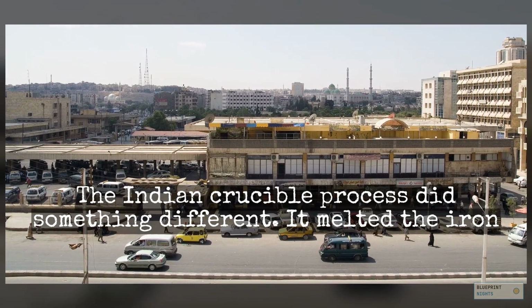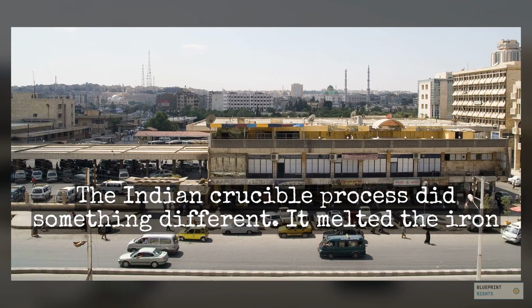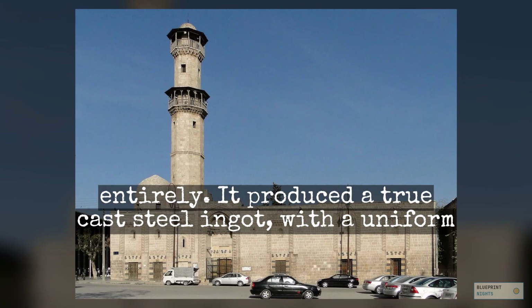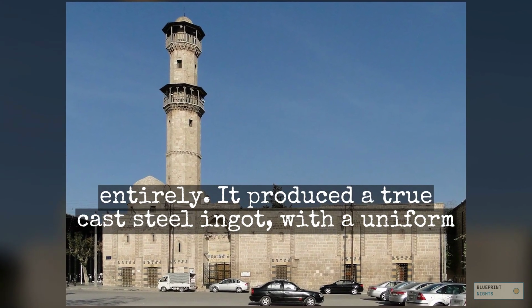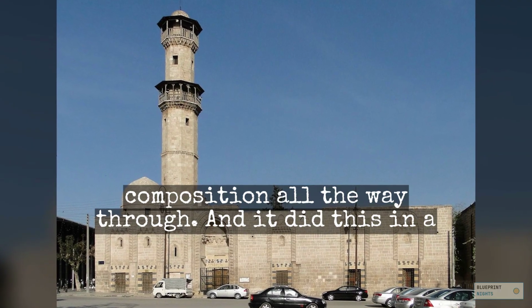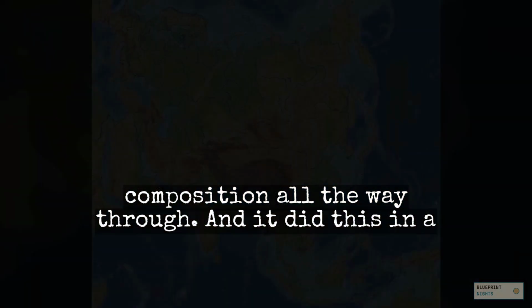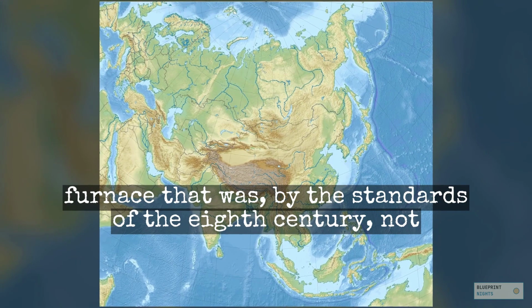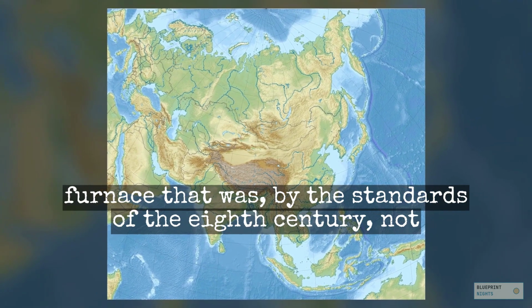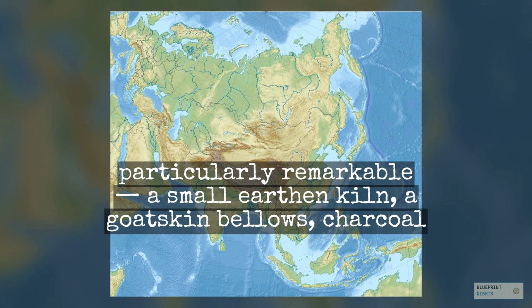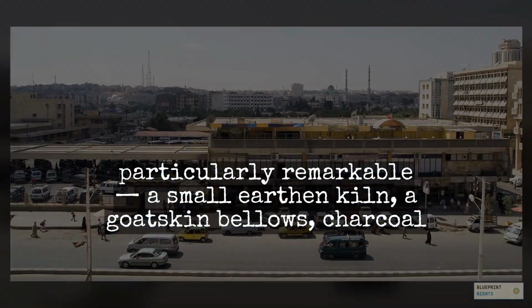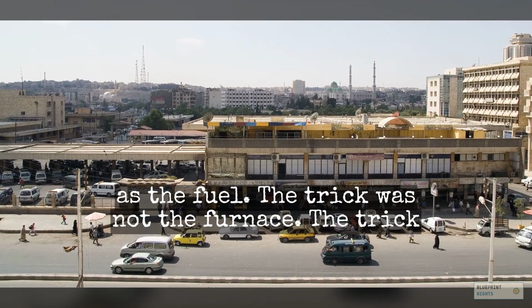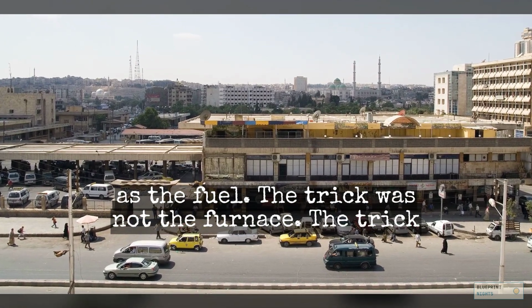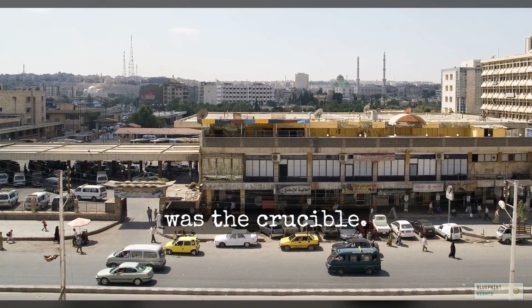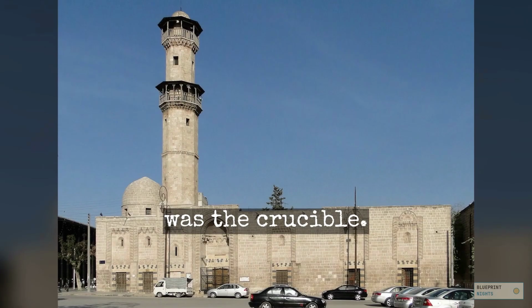The Indian crucible process did something different. It melted the iron entirely. It produced a true cast steel ingot with a uniform composition all the way through. And it did this in a furnace that was, by the standards of the 8th century, not particularly remarkable. A small earthen kiln, a goatskin bellows, charcoal as the fuel. The trick was not the furnace. The trick was the crucible.